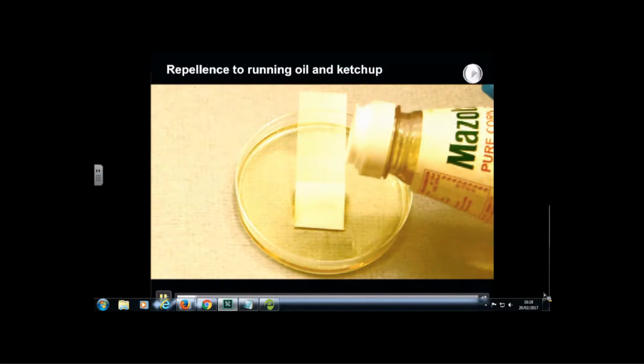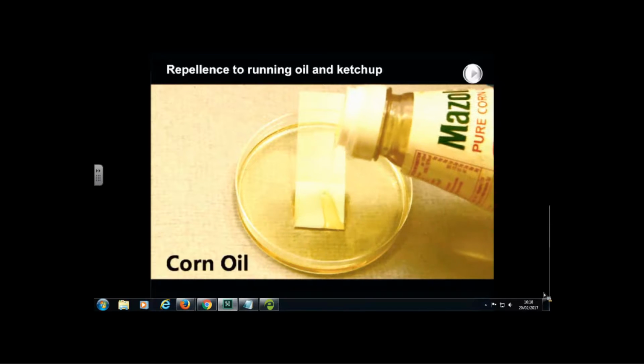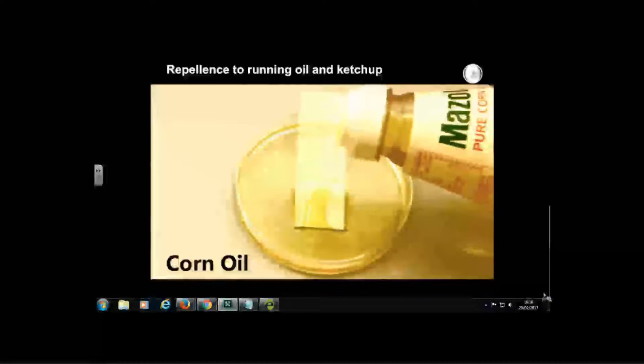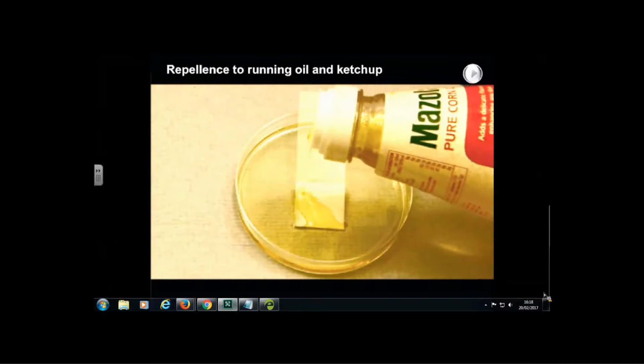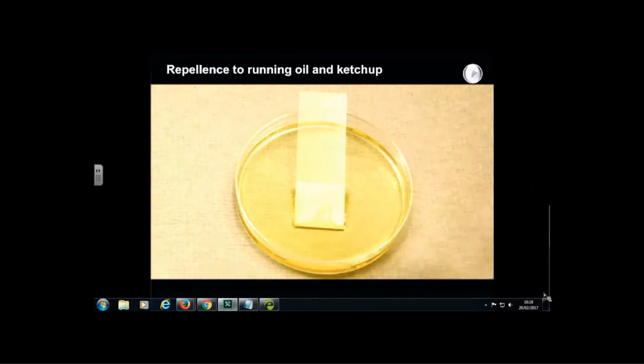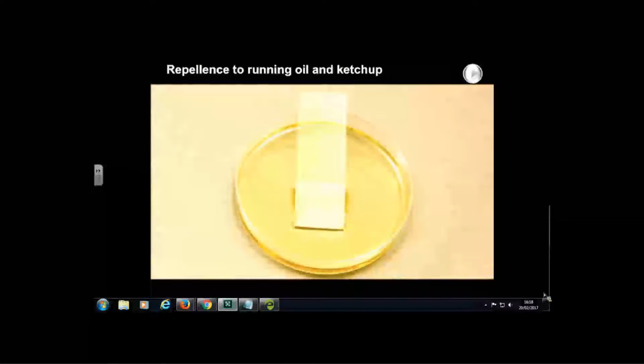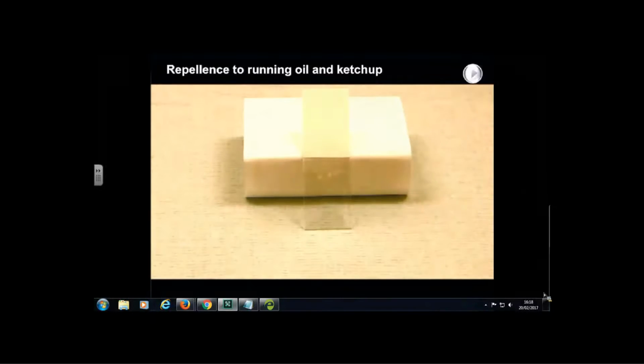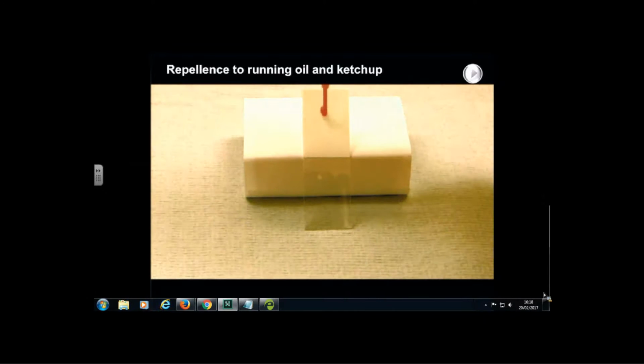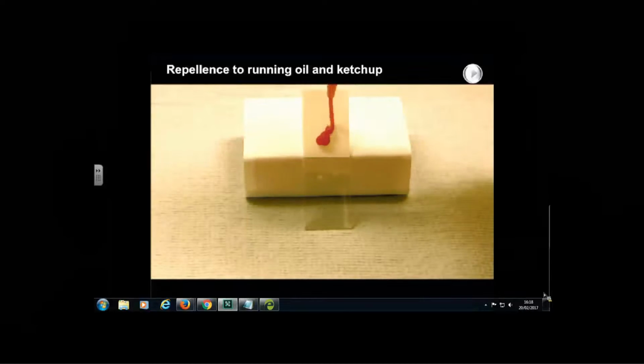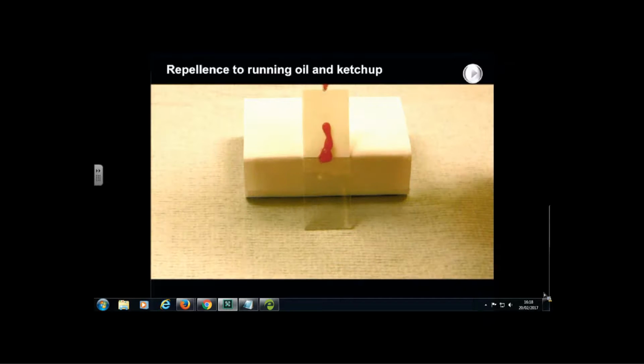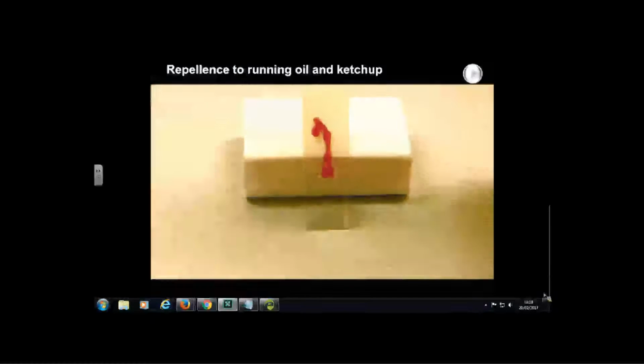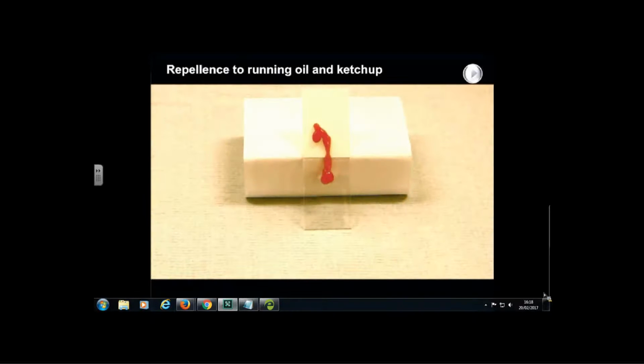This is showing repellence to oil and ketchup on the surface. This is corn oil on the surface, and you see it will not stick to the slip surface and will run off very readily. We also did a little test with ketchup from McDonald's on our surface, which again will run off the surface and won't stick to it.